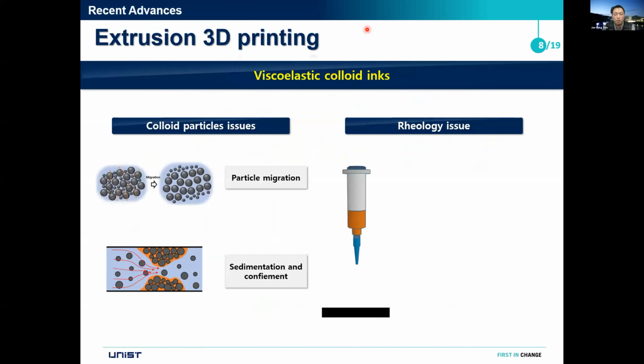So generally, people have used the extrusion-based 3D printing process for thermoelectrics. This process is a dispensing-like process, and ink is deposited layer by layer to make a 3D structure. In this process, we have to solve two material issues in inks. The first issue is colloidal particle issues, such as particle migration, sedimentation, and confinement. Secondly, the rheological issue. The first issue can be solved by good dispersion of the particles into the medium. The second issue is more important, and typically the 3D printable ink should have appropriate rheological properties, such as flow under pressure and maintaining structural integrity after deposition.